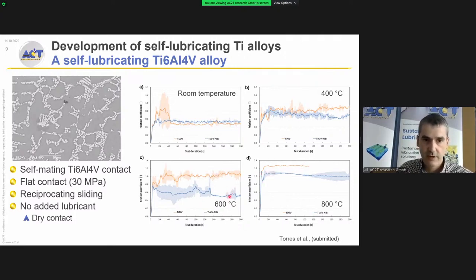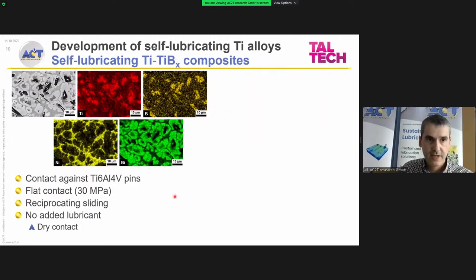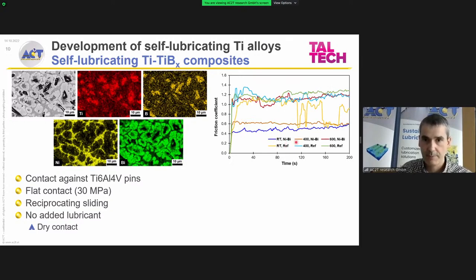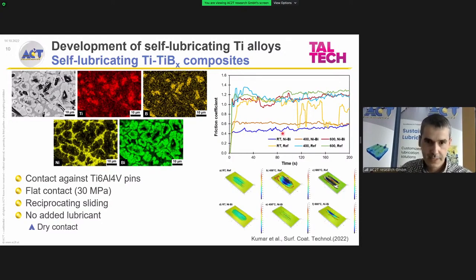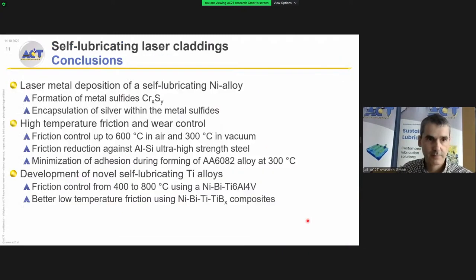The best conditions for this self-lubricating titanium alloy are at 600 degrees, where we get a relatively good and low coefficient of friction of around 0.5. Again, self-mating titanium alloy without any lubricant at all. And finally, we came to our colleagues from Tallinn. They are working in powder metallurgy, developing titanium boride composite materials, and we also applied this nickel bismuth addition, and we ended up having this titanium boride titanium phase surrounded by bismuth, and this bismuth phase is surrounded by nickel. We repeated these experiments, also under very detrimental conditions, self-mating titanium contact, and we see that in this case, especially at the lower temperatures, room temperature and 400 degrees, friction in a titanium self-mated contact can be as low and steady as 0.4. And not only does friction get better, but compared to the self-mating titanium contact, the wear also becomes much better.